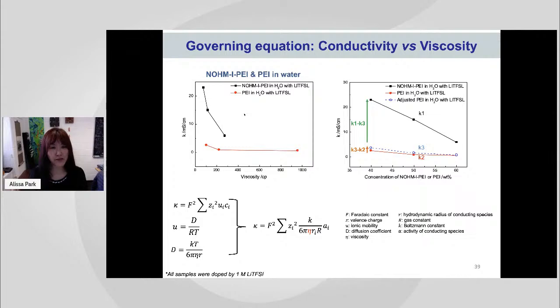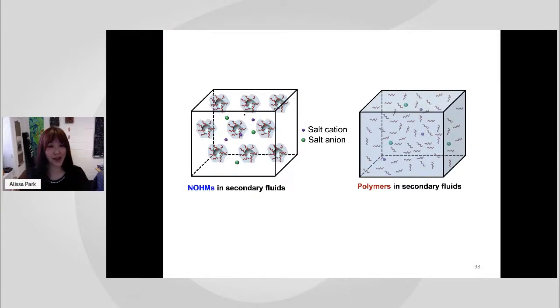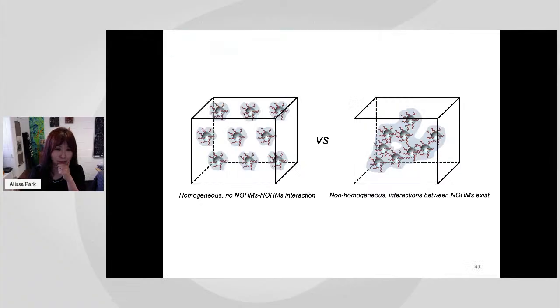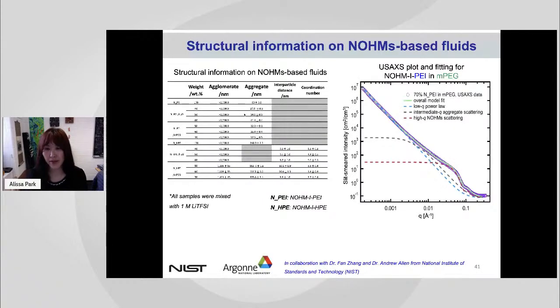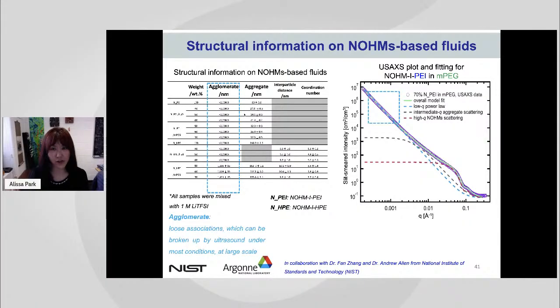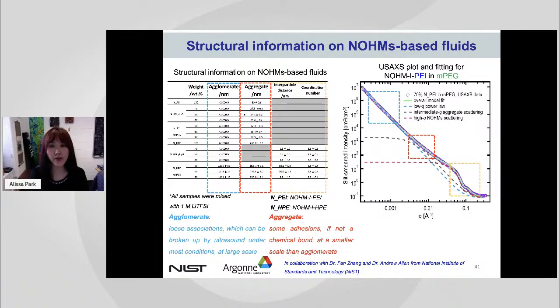Why? Because compared to these two systems, the only difference is the NOHM system has a lot of nanoparticles, which should not contribute to conductivity, or it should increase the viscosity. So we got confused. So we started thinking that maybe the picture on the left, which is a fully distributed NOHMs, equally homogeneous mixture, is not the real system. Maybe there is some clustering happening, which we didn't think about. So in order to really understand this, we went to synchrotron. If you look at the USAXS data on the right-hand side, in the Q range, if you think about just nanoscale fluids or nanoscale materials, you should have only signal at high Q range because Q is the inverse of the length scale. But we start to see a lot of signals at the low Q range, which is telling you that there's something chunkier and bigger than what we expected.